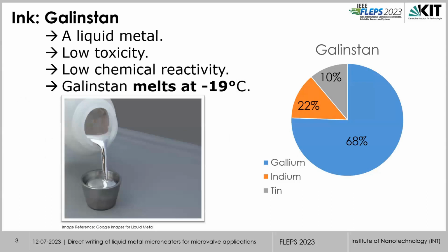So throughout this talk, when I'm mentioning liquid metals, I'm using this Galinstan. It is a gallium based liquid metal. As we say liquid metal, it is the metal which is liquid in nature. For Galinstan, the melting point is around -19, and Galinstan is a mixture of 68% gallium, 22% indium, and 10% tin.